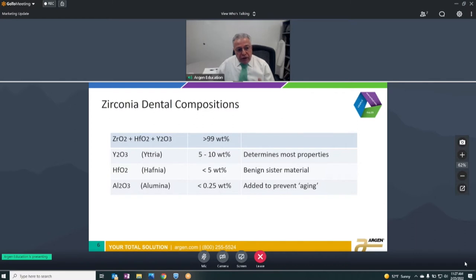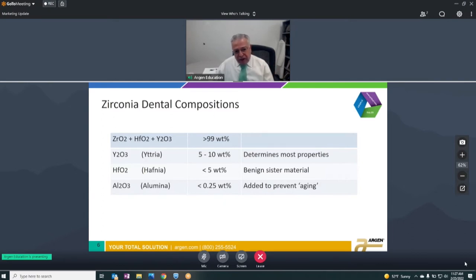For zirconia, the compositions are very simple — 99% of it is zirconia, a little bit of hafnia, which is a sister element you can't remove 100% from zirconia, and then the yttria. When we add coloring oxides, they make up less than half a percent — certainly less than one percent. There are very small transition elements like iron, erbium, manganese, or cobalt, and they get locked into the lattice structure when they form a color.